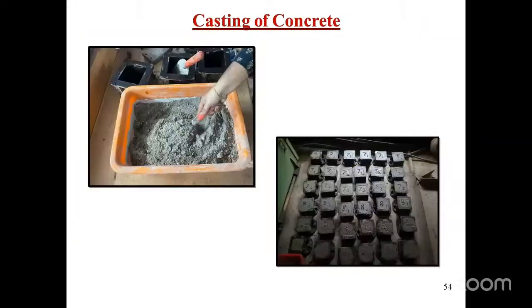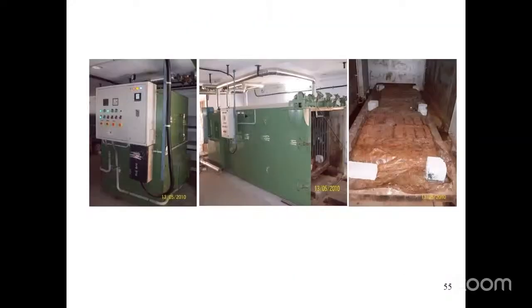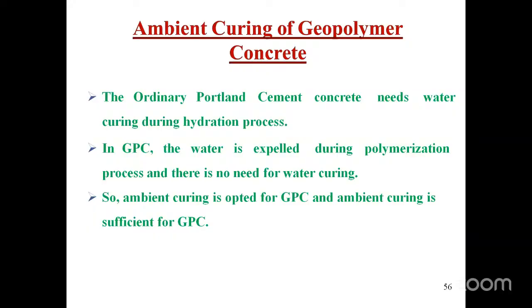The advantage of geopolymer concrete is curing. So initially, people tried this geopolymer concrete with hot curing. With 24 hours of hot curing, we can get the 28-day compressive strength of concrete as obtained from conventional cement concrete. In that case, only fly ash was used. Nowadays, the scenario is changing. Introduction of GGBS in geopolymer concrete eliminates this hot curing or steam curing. Very simple sunlight curing, that is called ambient curing, is enough to get the compressive strength of concrete. Even with 24 hours of air curing, you can get the strength of concrete as obtained from the conventional cement concrete. So this is the specialty of this concrete.